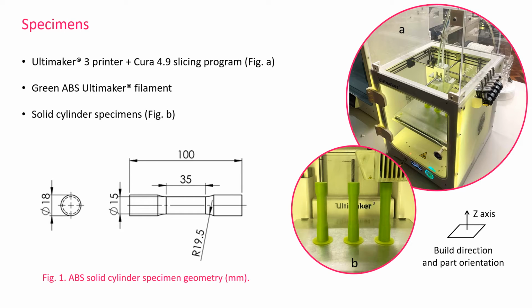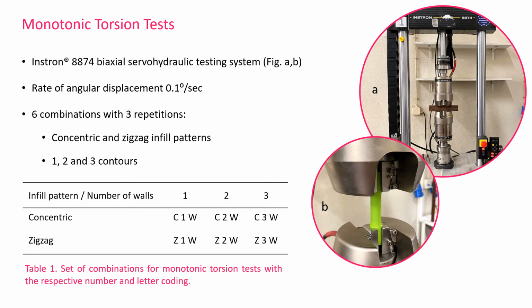Specimens were printed in the upright orientation since support structures would be required if specimens were printed in the XY orientation, as shown in Figure B. Instron 8874 biaxial servohydraulic testing system was selected to perform monotonic and fatigue tests, shown in Figure A and Figure B. Monotonic torsion tests were conducted with a rate of angular displacement of 0.1 degrees per second.